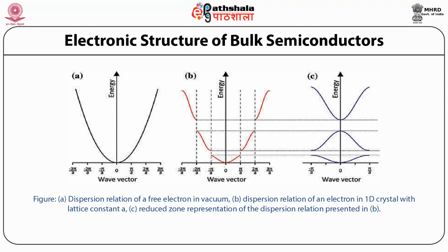This results in considerable disparity in energy of these standing waves, since the first wave concentrates electronic probability at ions, thereby reducing the potential energy, while the second one amasses the probability of electrons in the middle of the ions. Therefore, because of the disparity in electron charge distributions, these standing waves possess dissimilar energies at identical k value, resulting in an energy gap within the dispersion relation.